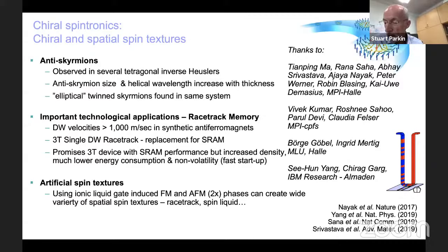They're equivalent. But what's super interesting, let's say we take a system like manganese-3 tin, manganese-3 germanium, which is a chiral antiferromagnet. And in these systems, you can change the chirality from clockwise to anti-clockwise by a small in-plane magnetic field, because the structure actually has a small uncompensated magnetic moment. And so the chirality of the structure is really important. It gives rise to, for example, an anomalous Hall effect. So a system which has no net magnetization can give rise to large anomalous Hall effects related to the chirality. So you change the chirality from clockwise to anti-clockwise by an in-plane magnetic field.